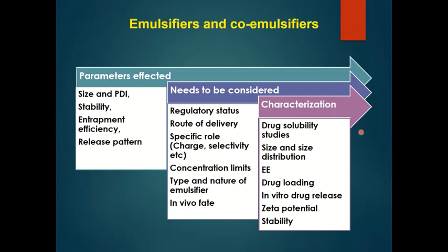What happens? We are adding the drug in the lipid phase and then dispersing that lipid phase into the aqueous phase. So if the drug is having more partition or more affinity towards the aqueous surfactant solution, then all the drug will leach into the aqueous surfactant solution only. So there will be a decrease in drug loading and entrapment efficiency. So you need to perform drug solubility studies and see how much drug is going into surfactant.